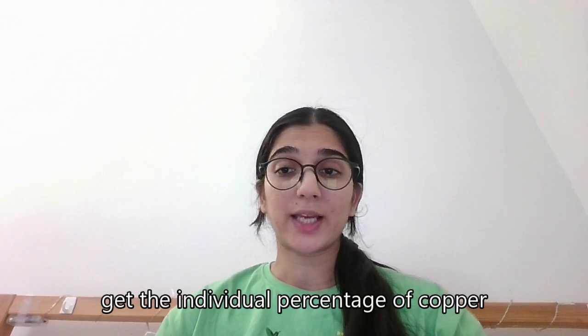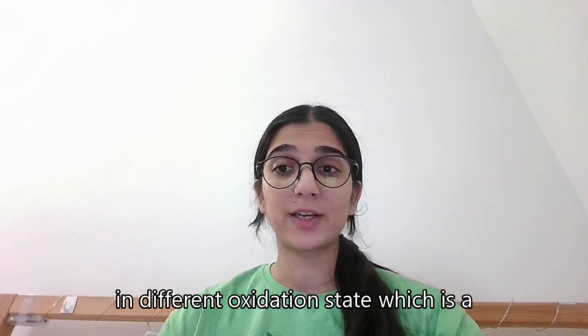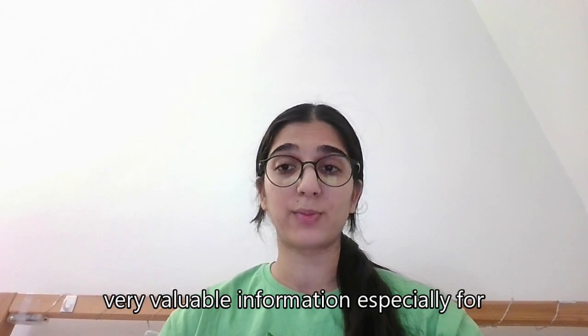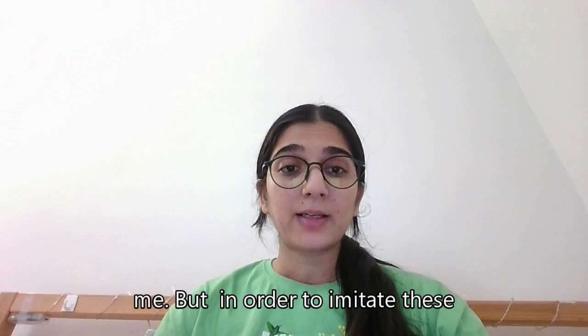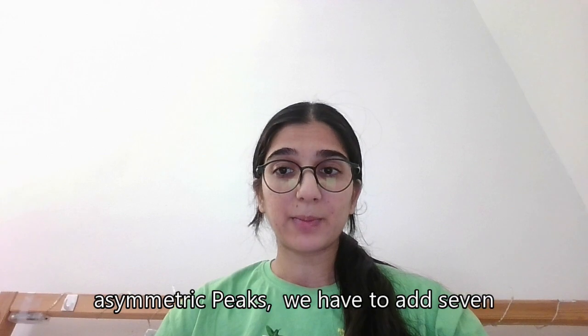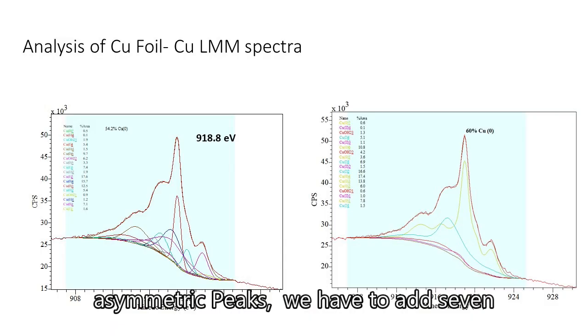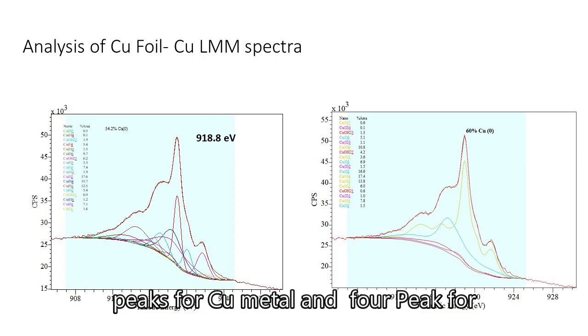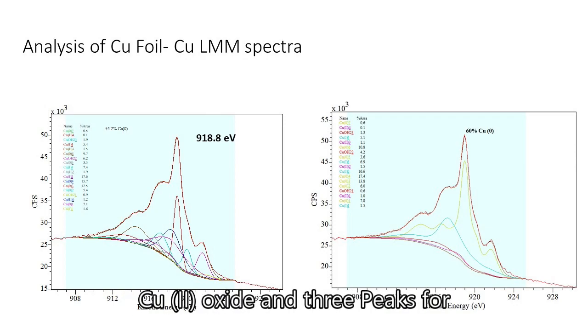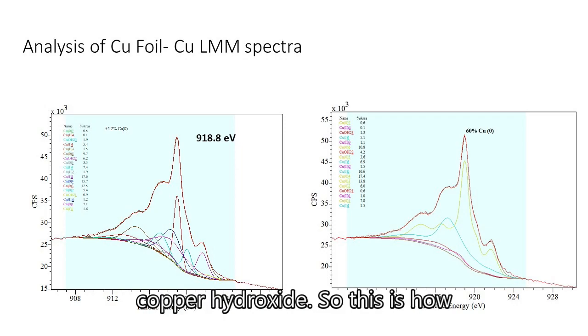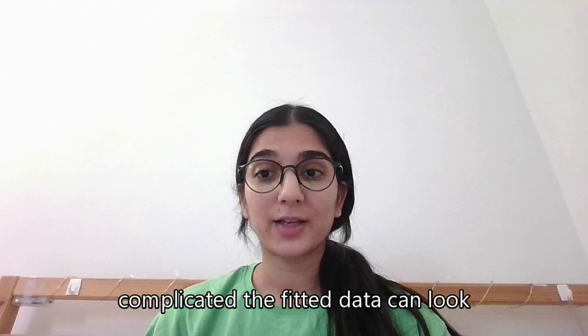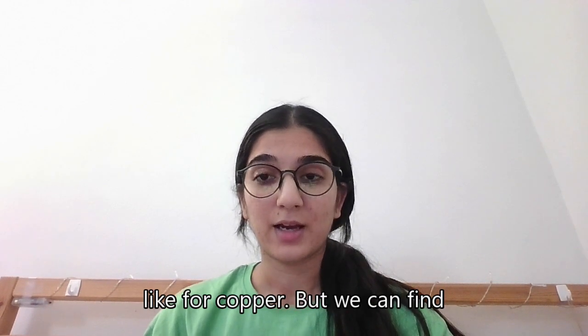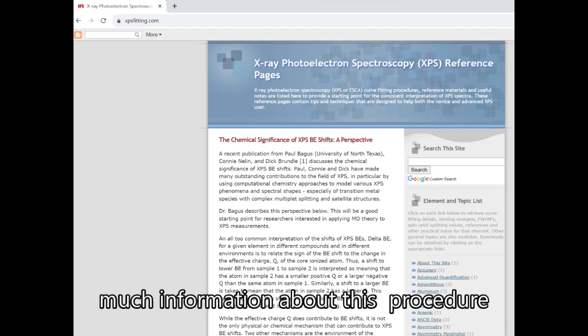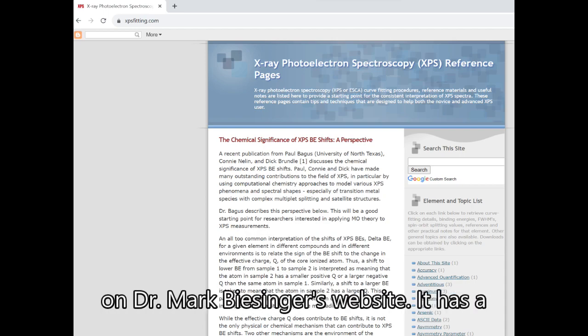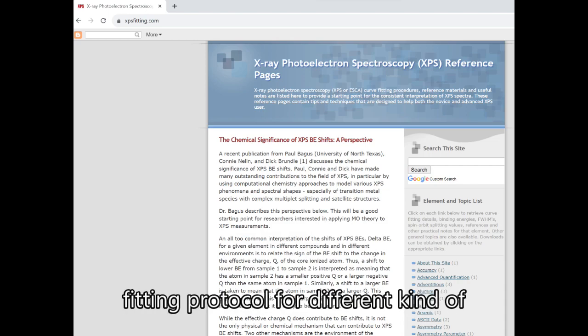But once we fit it, we can get the individual percentage of copper in different oxidation states, which is very valuable information, especially for me. But in order to imitate these asymmetric peaks, we have to add 7 peaks for copper metal, 4 peaks for the copper 1 oxide system, 4 peaks for copper 2 oxide, and 3 peaks for copper hydroxide. So this is how complicated the fitted data can look for copper. But we can find much information for these procedures on Dr. Mark Biesinger's website. It has a fitting protocol for different kinds of elements, which is very useful.